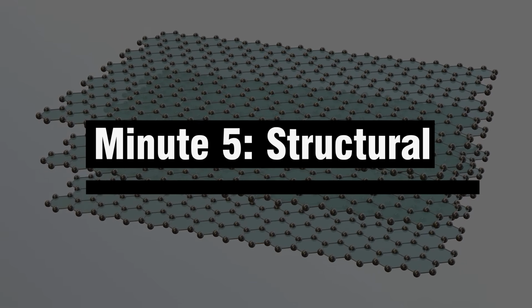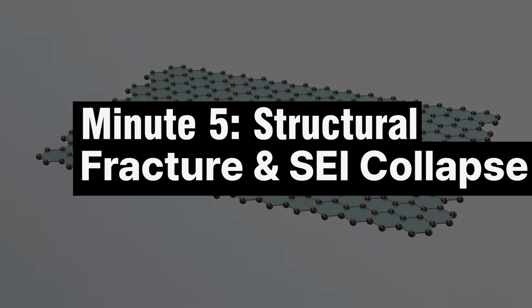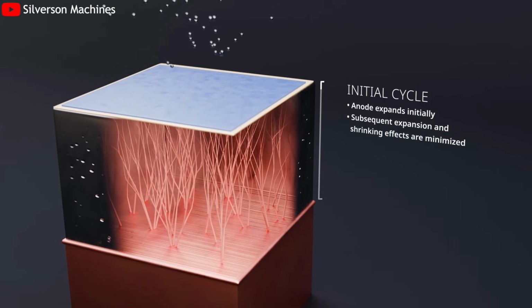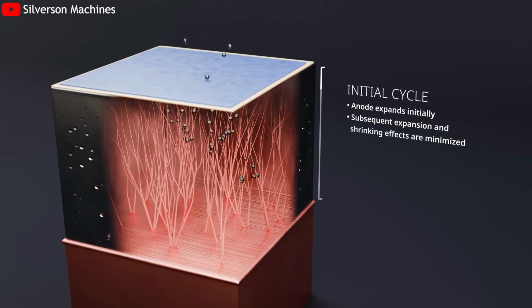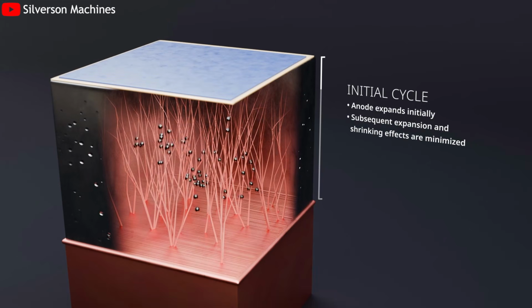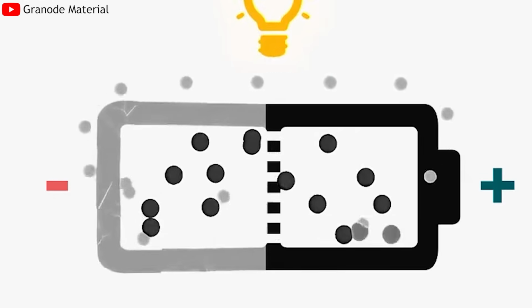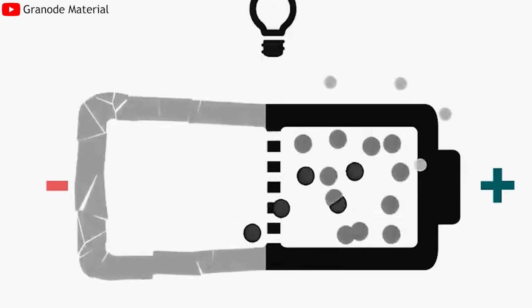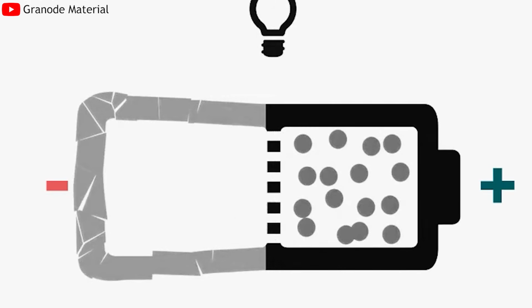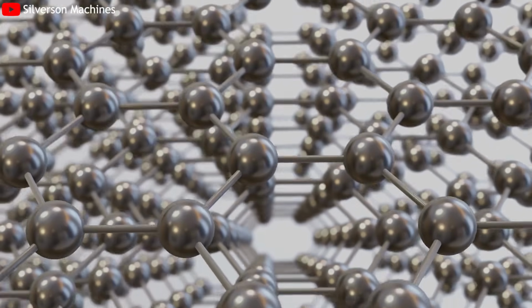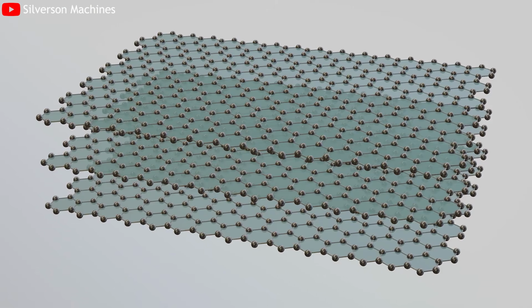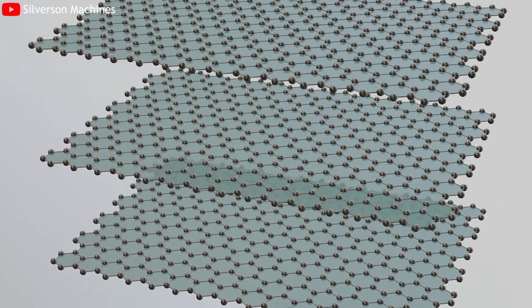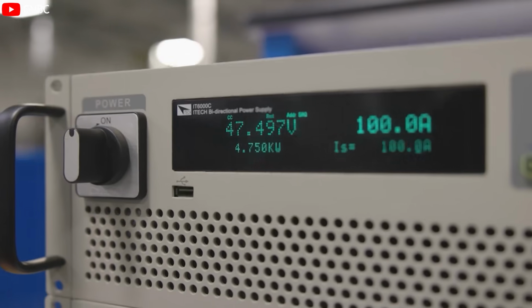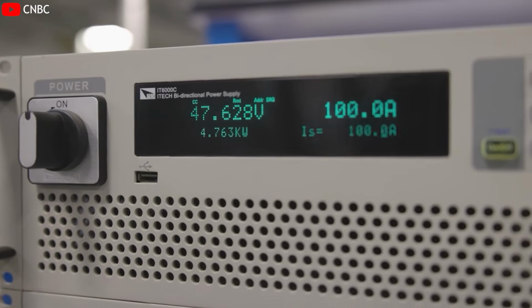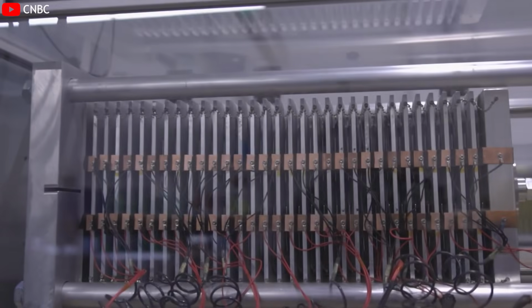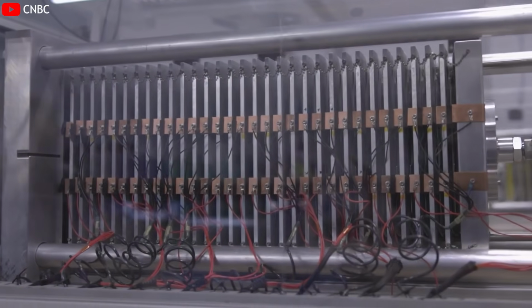Minute 5. Structural fracture and SEI collapse. By minute 5, the damage becomes structural. The battery reports 100%, but physically, it has aged months or years in minutes. The solid electrolyte interface, a microscopic protective layer on the anode, is critical for longevity, but it is fragile. High current charging causes violent volume expansion. If silicon is used, the anode can expand by up to 300%. A 5-minute charge turns that expansion into a mechanical shock, cracking the solid electrolyte interface like an eggshell.